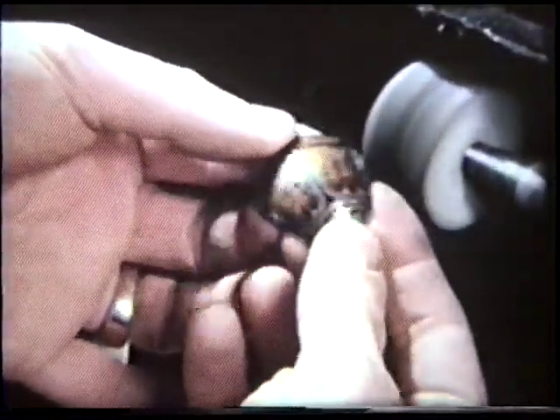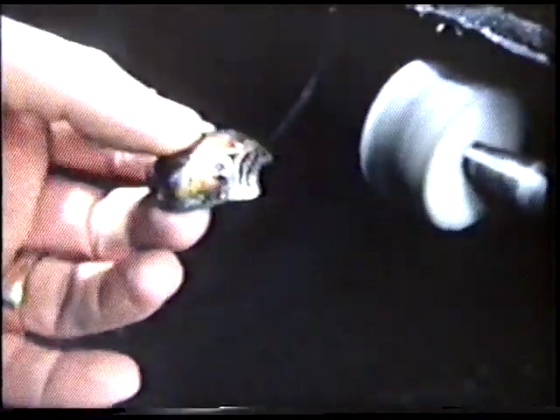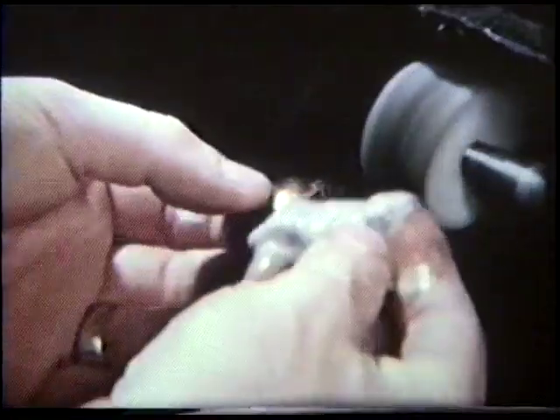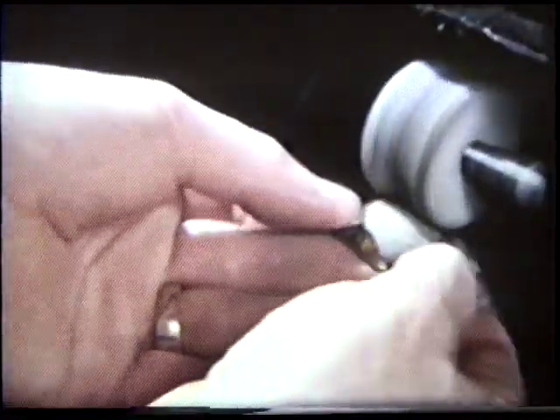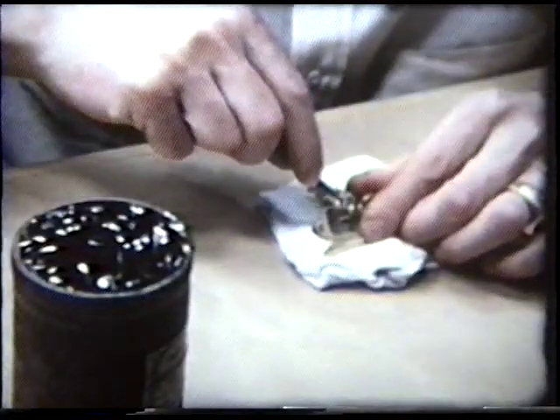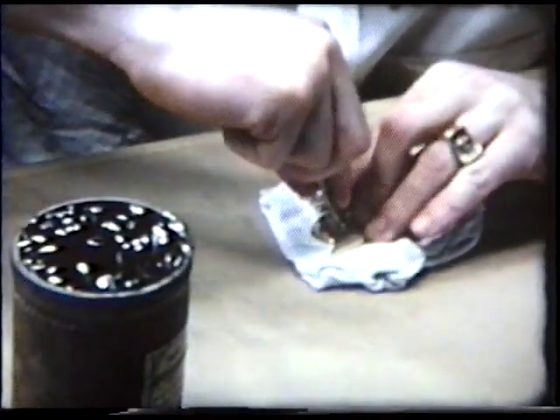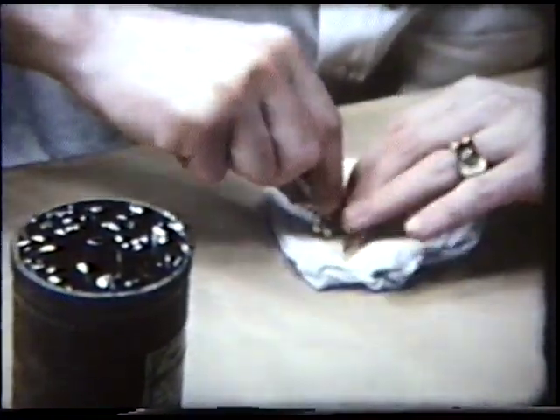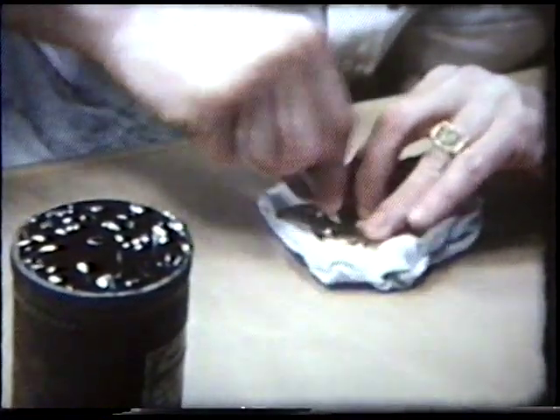A mixture of pumice and water on a hard felt buff polishes both the enamel and the gold cloisons. White rouge on a muslin buff will complete the polishing of the surface. As a last step, the two sections are fastened together by turning over the edge of the tube which forms the rivet. Also on the back of the piece are the safety clasp and the joint which will hold the pin stem.